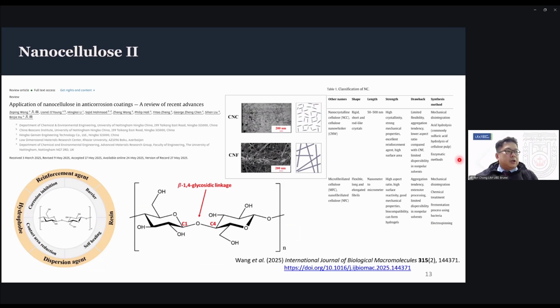One thing I want to say from this slide is that you can deploy nanocellulose in mainly three areas: as reinforcement fillers, to improve the hydrophobicity of the coatings, and you can also functionalize the nanocellulose to improve their dispersibility. Because one of the issues is that if you just use nanocellulose on its own without any functionalization, the particles can have large surface area and large surface reactivity.